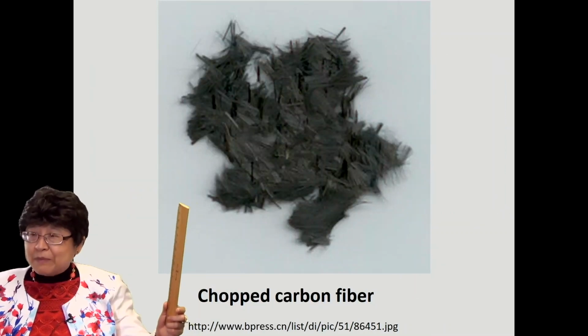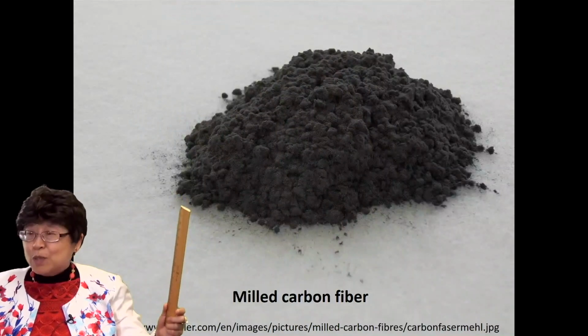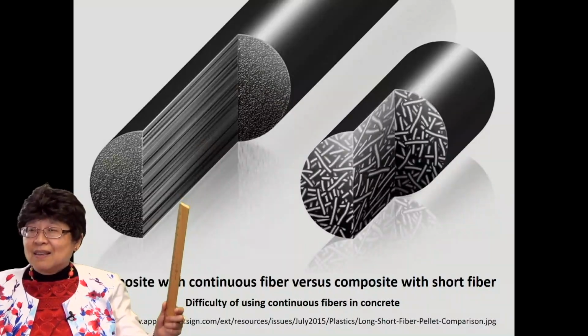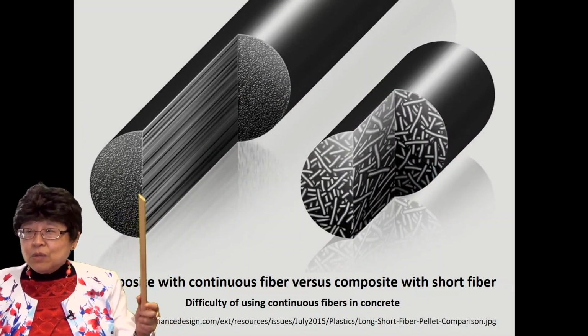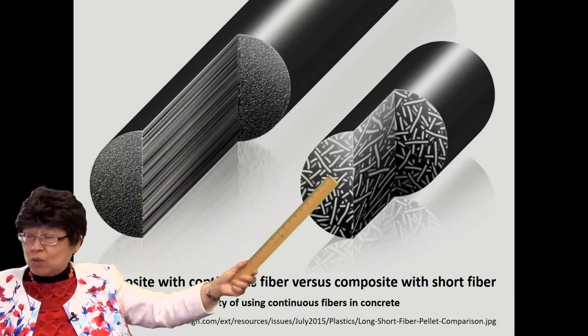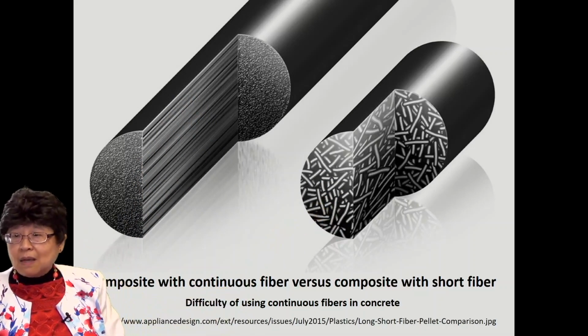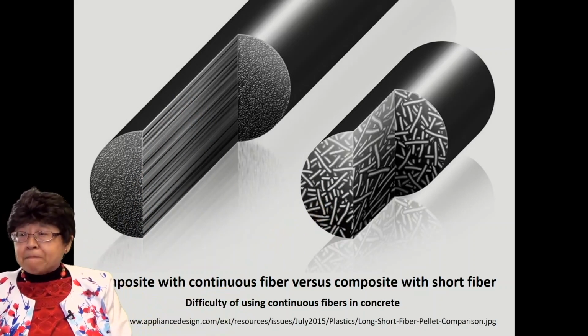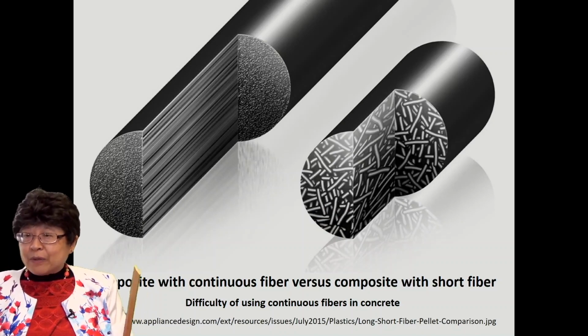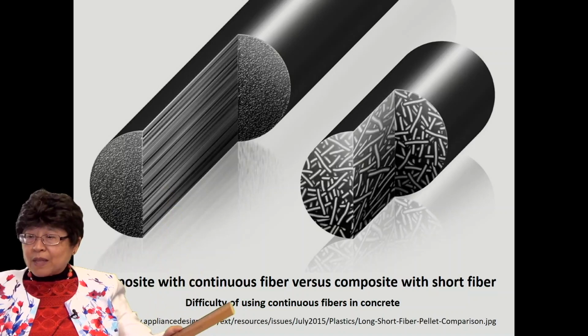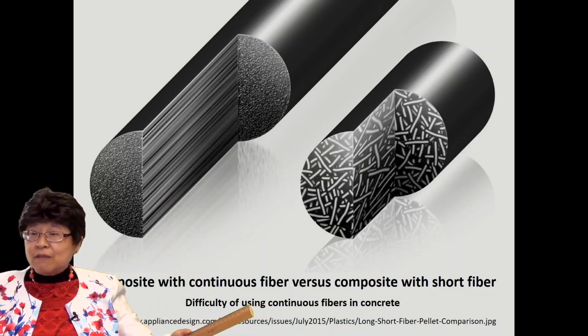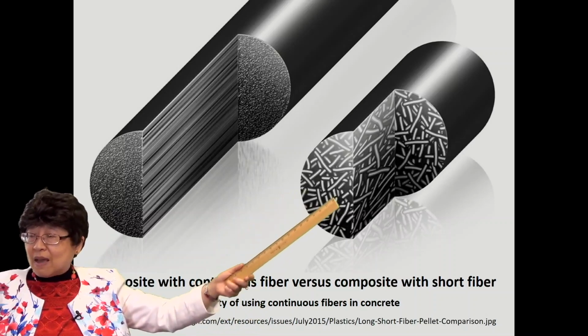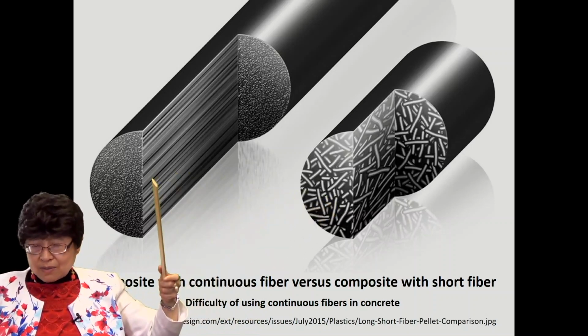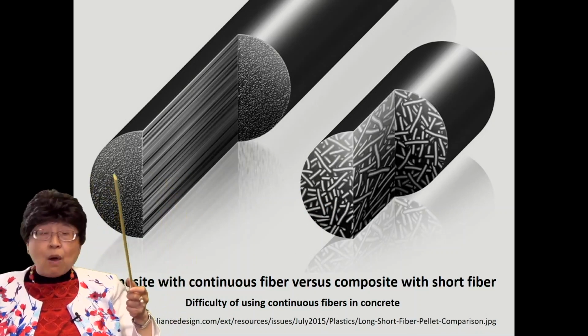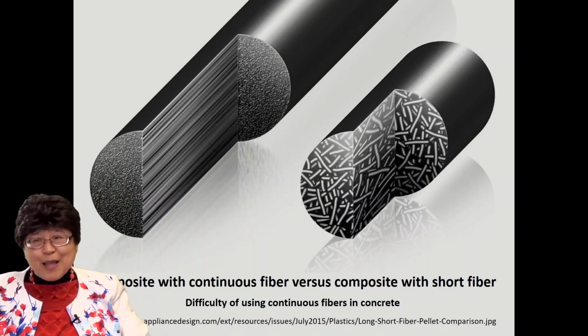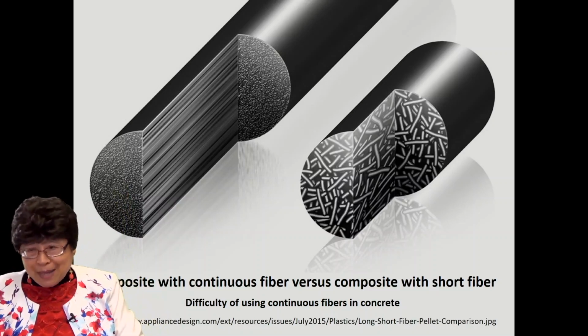Also, there are chopped carbon fibers and milled carbon fibers, which are even shorter than the chopped ones. And in general, one can use the continuous fibers or the short fibers as a reinforcement to make a structural composite. However, for the case of concrete, using fibers in concrete, the short ones are much better off than the long ones because you cannot throw the long ones into the cement mix. You have to lay them down.